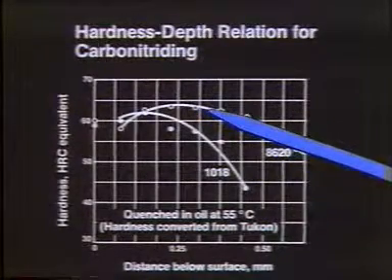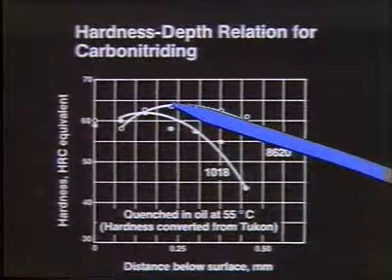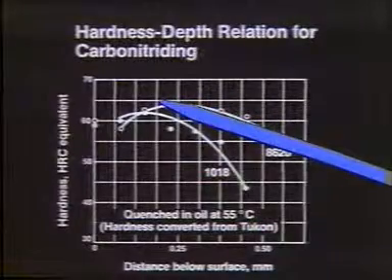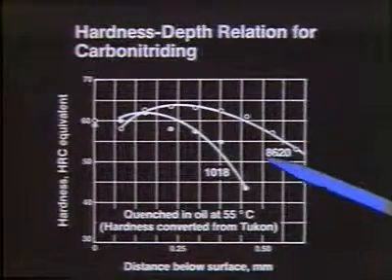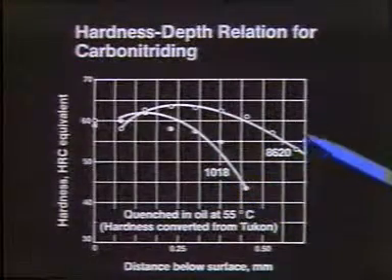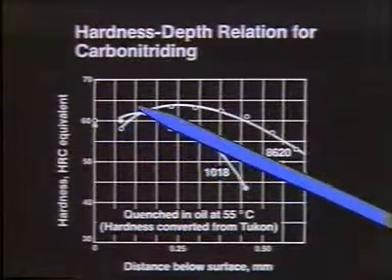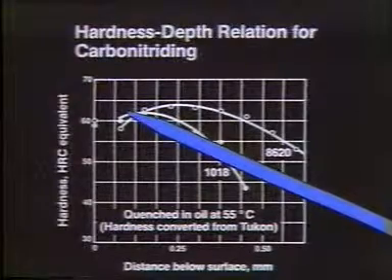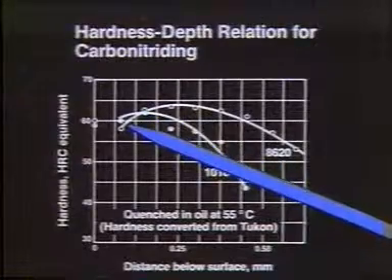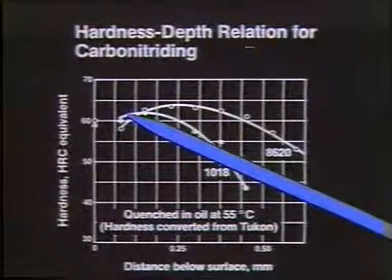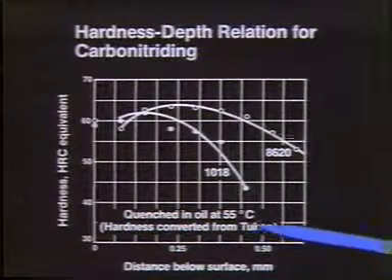We find that the hardness is going to be directly related to the carbon content. So as the microhardness drops off, it means the carbon content is decreasing. You notice that for 1018 steel it's entirely different from an 8620 steel. And you notice in the surface of the material we have a decrease in hardness as well — that's actually due to decarburization of the surface, meaning at the end of the cycle the surface was decarbed and we didn't have as much carbon in that area.